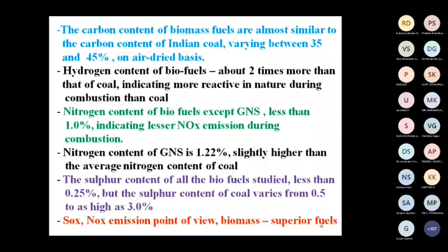The carbon content of biomass fuels is almost similar to the carbon content of Indian coal, varying from 35 to 45% on as-received basis. The hydrogen content of biofuels is about 2 times more than that of coal, indicating they are more reactive in nature during combustion than coal. The nitrogen content of biofuels, except groundnut shell, is less than 1%, indicating lesser NOx emission during combustion, fuel NOx. The nitrogen content of groundnut shell is around 1.2, slightly higher than the average nitrogen content of Indian coal. The sulfur content of all biomass fuels studied is less than 0.25, but the sulfur content of coal varies from 0.5 to as high as 3%. We have some high sulfur coals in India. So from the NOx emission point of view, biomass fuels are superior fuels.